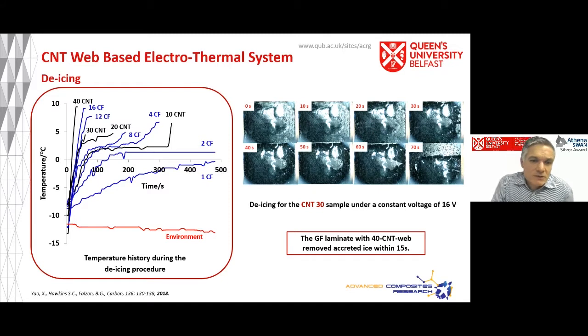Now, what you will note again is that you get a different response in terms of the time taken to remove the ice, depending on the number of CNT webs that you use in your assembly. Now, with 40 layers of CNT web, the accreted ice was removed in about 15 seconds, so it was pretty quick.